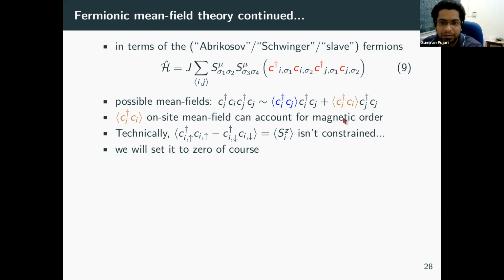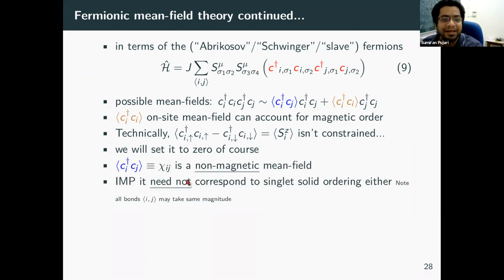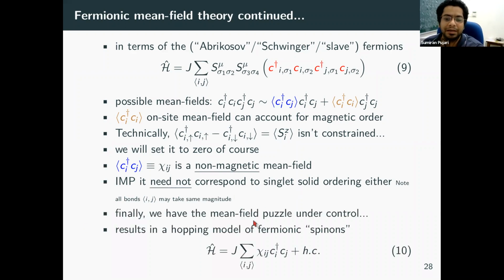So in this olive colored term, you see the mean field is coming from a single site, this i, j index being the site. So this is an on-site mean field, and this can account for the same kind of magnetic order that was taken into account in the spin wave theory as well. So the fermionic way of setting up the theory can actually account for magnetic order. We will of course set this mean field to 0. And therefore the non-magnetic mean field actually comes from this other kind of mean field decomposition, which leads to a hopping process between different sites of these fermions. So this is a bona fide non-magnetic mean field. And importantly, it need not even correspond to a singlet solid ordering. It in principle can, but it need not. And therefore we have the mean field puzzle under control.